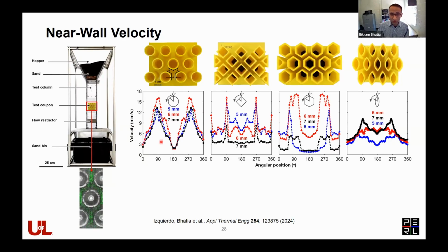And hexagons are quite interesting. You have really high velocities along these sidewalls, again, which is a streaming flow as the particles rush through. But you have, again, a large void area on the bottom.